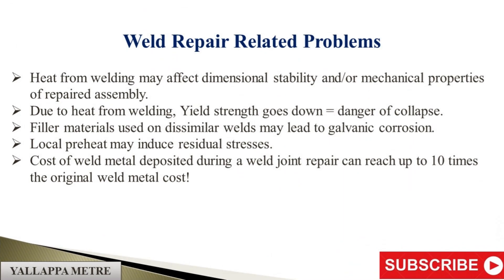Weld Repair Related Problems: Heat from welding may affect dimensional stability and/or mechanical properties of the repaired assembly. Due to heat from welding, yield strength goes down, which equals danger of collapse. Filler materials used on dissimilar welds may lead to galvanic corrosion. Local preheat may induce residual stresses. Cost of weld metal deposited during a weld joint repair can reach up to 10 times the original weld metal cost.